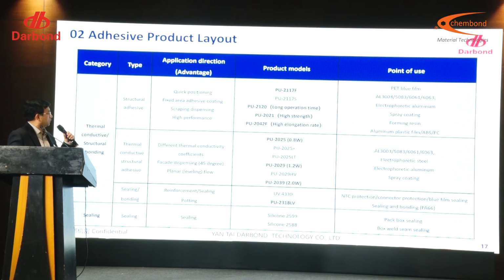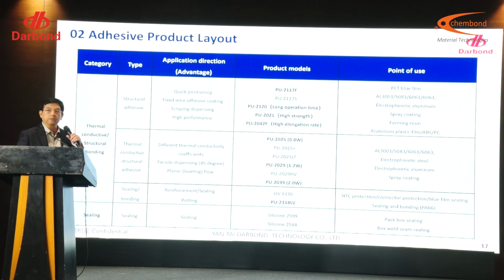For the thermal conductive structure adhesive, you have to use it on aluminum, also electrophoretic steel and aluminum, and you also have to contact some spray coatings. Then for the reinforced sealing and potting, you have the thermocouple protection, connector protection, blue film sealing, and sealing and bonding. Sealing is more like these three materials. We talk about thermal conductive structure bonding, which is more like a two-part PU with different thermal conductivity. For the sealing, we more often use silicone.